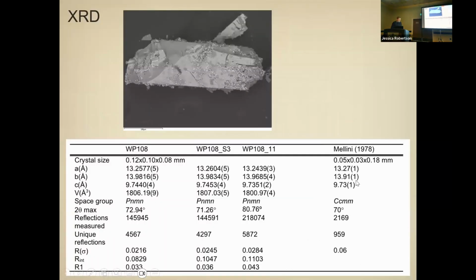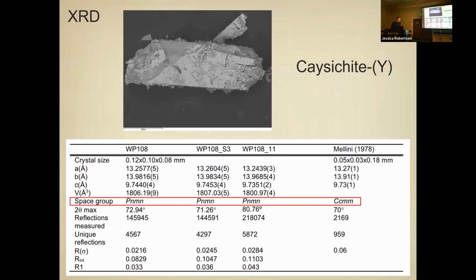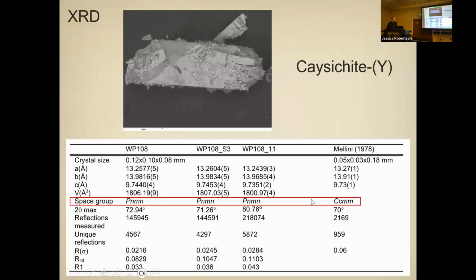good agreement with a mineral which was described in 1974, and then later with the structure in 78, which would be caysichite. Yeah, we'll talk more about this in a minute, but there is something very confusing. And then while everything agrees, the unit cell dimensions, the space group is different. So we have actually, instead of this PNMN group, a centrosymmetric group.